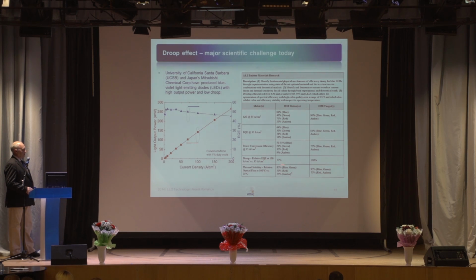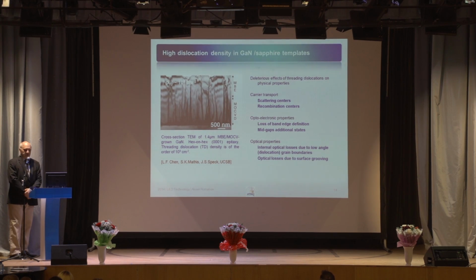And the droop effect nowadays is 70%, and it is expected that when we can get out of this effect, we will have this 100% possibility to use very high density current, and therefore to go to very small LED devices. And of course, thermal stability is here. And the main reason for this droop effect, and now I have already moved to the physical part of the talk, is the presence of various types of defects in the material that is used.